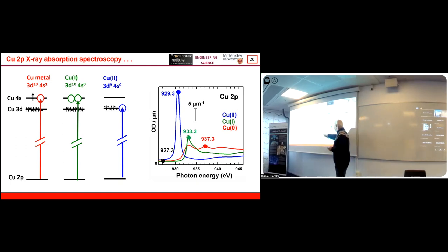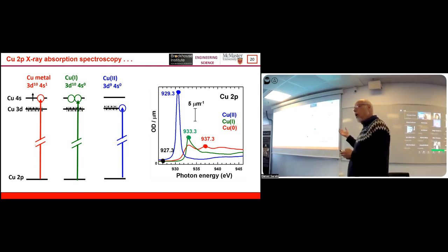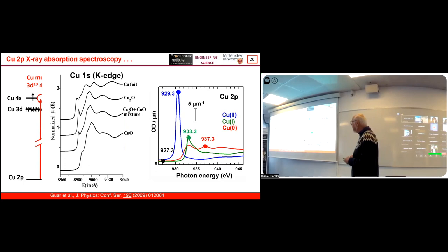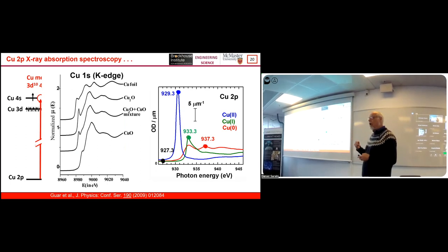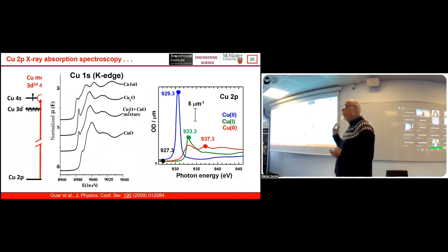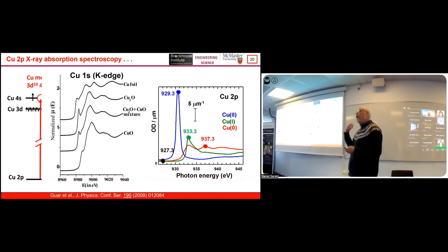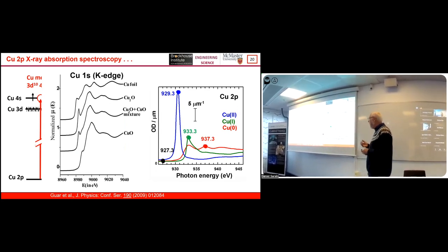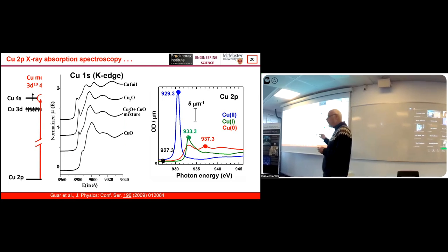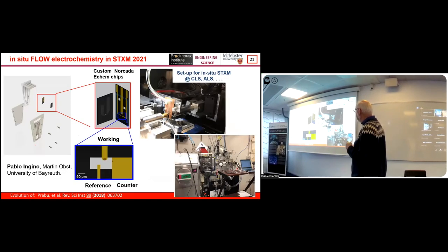And we can take this energy, that energy, that energy, and that energy, and decompose the chemistry in as accurate a way as if we take 50 or 100 energies to get the spectroscopy. And in contrast, at the K shell, you can see you don't have the same leverage. Why? Because that 1s level wants to go to p's, and the p's go on to the d's, which are the chemically active electrons in 3d transition metals. You need to have asymmetry to get these very weak s to d transitions that are only weakly allowed.